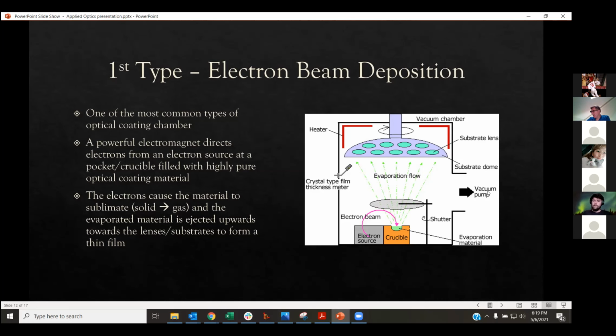So there's a number of reasons why you want to pump out the air. You don't want your coating material to interact with the air molecules or basically slow them down from getting here. You wouldn't have as high a packing density, and the packing density, or the density of the film, is directly related to the refractive index that you end up with. The other reason is you can trap water and air molecules within the film, and that's another reason why your index would come out very strange, and your film would not be a very good one. It would probably also cause mechanical problems over time, right? I would imagine that the oxygen in the air and the water are both highly reactive, so that might cause some deterioration. Yeah, exactly. It totally affects the durability as well. So that's basically how electron beam deposition works.